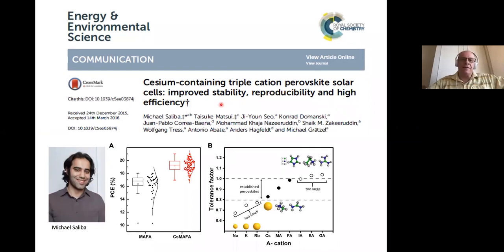This composition engineering became quite a drive for us, and Michael Saliba, here, postdoc at the time, now will be leading PV activity in Germany as a professor. Seok was also working on this. Developed what we call the triple cation recipe, which has been kind of a reference composition in the community from then. The interesting thing with adding cesium to the formamidinium methyl ammonium is that it improves the quality of the grains, so we can get over 20% efficiency.